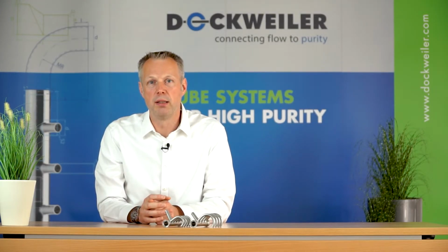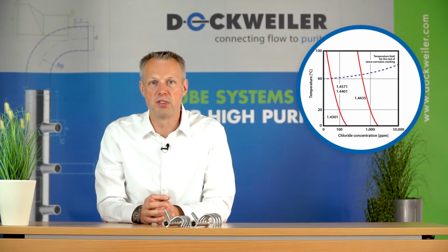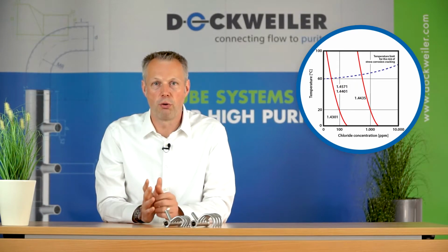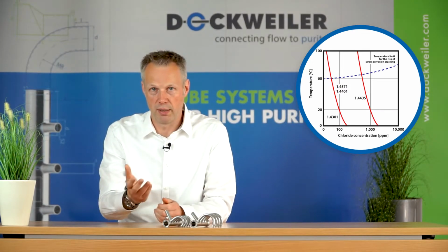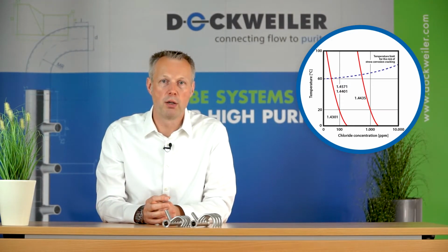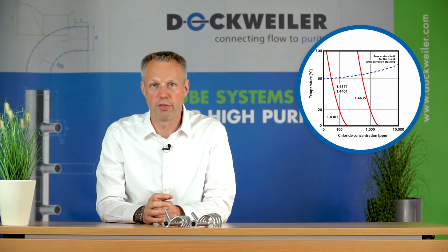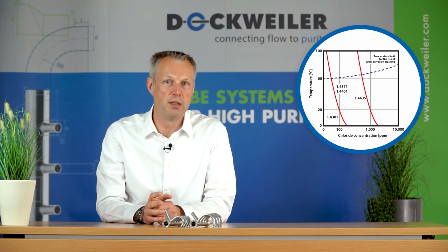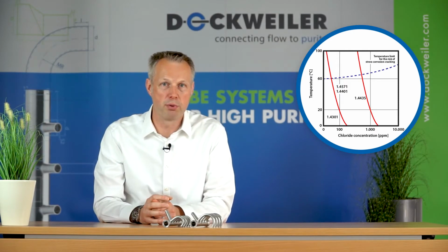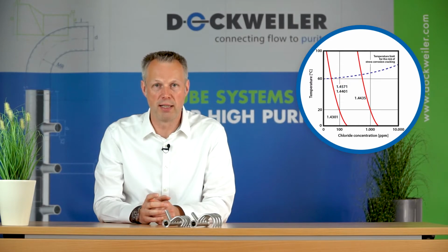However, when we are looking into the facts, you will see with regard to this picture here that chloride-induced corrosion with regard to either 304L or 316L happens already at pretty low chloride concentrations. These chloride concentrations are varying, let's say, in between 100 or 1000 ppm, which is then in return roughly 0.1% chloride concentration. So you can see this is happening at pretty low concentrations already.